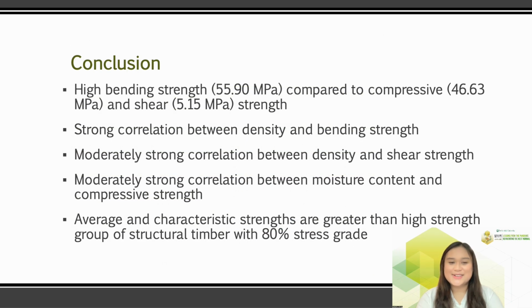To synthesize our study, Bambusa blumeana has a high bending strength as compared to its compressive and shear strengths. There is a strong correlation between the density and bending strength, while there is a moderately strong correlation between the density and shear strength and between the moisture content and compressive strength. Both the average and characteristic strength values of bamboo are greater than the high strength group of structural timber with 80% stress grade. Therefore, Bambusa blumeana can potentially be a substitute to timber as a construction material.